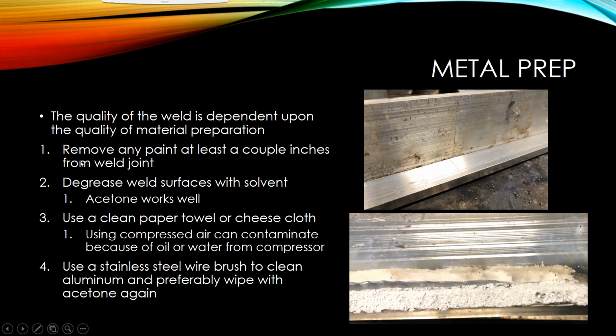So I got some steps that I like to do to make sure that you get that metal as clean as possible. First, you want to make sure that you remove any paint at least a couple inches away from the weld joint. And that's not only on the front side of the joint, but the back side as well, because whether it be a primer or paint on the backside, it can get drawn into the weld.